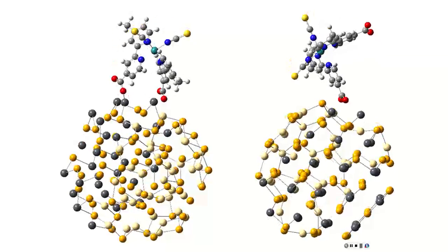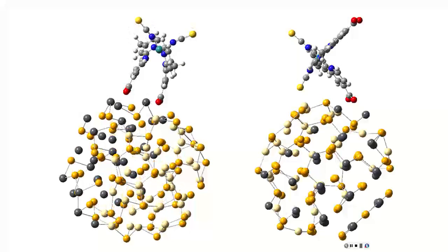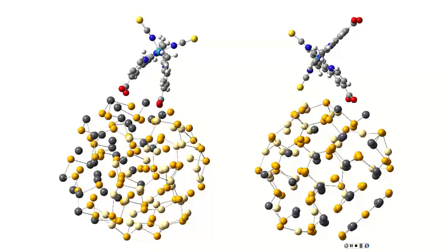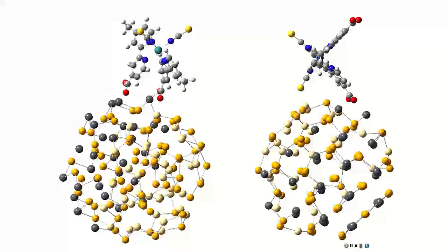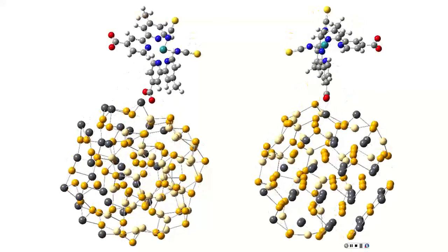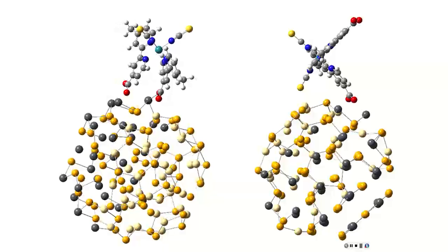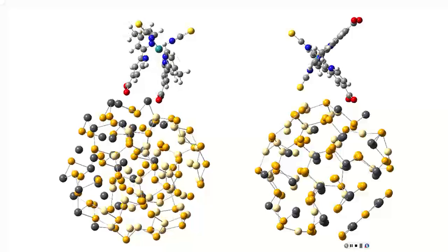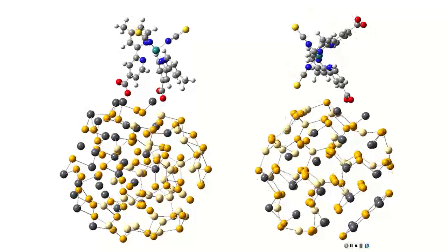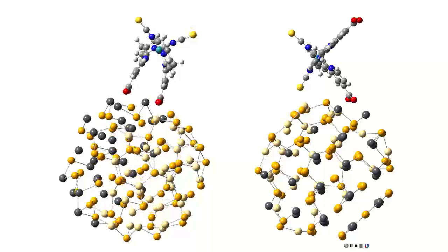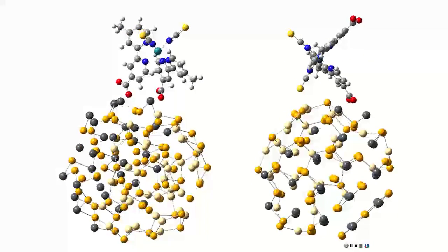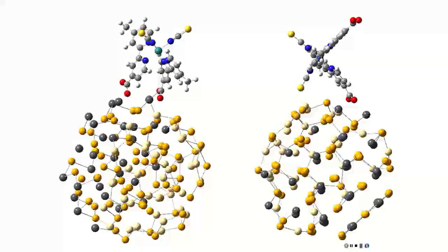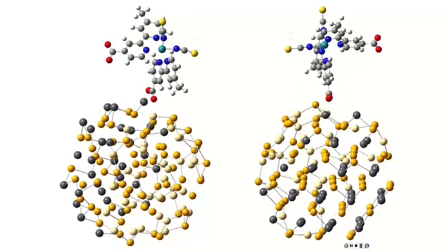And this rotation and reorientation probably really helps to minimize the overall total dipole moment, when both the dipole of the surface at the interface and the total dipole coming through the molecule should kind of compensate each other and hopefully provide the least possible dipole in the final structure. And this probably dictates the reorientation of molecules, that they want to go with both to the surface, right? Because when another one is going up, you are probably not compensating completely the dipole at the surface, since the dipole of the molecule is not as big if you reorient it this way.